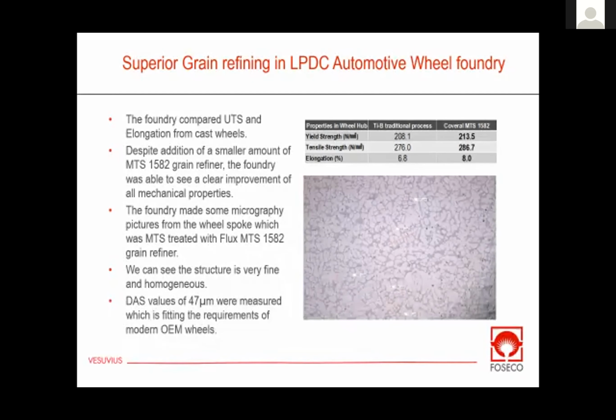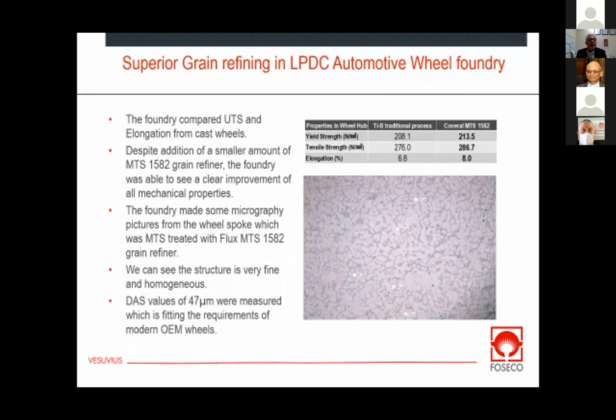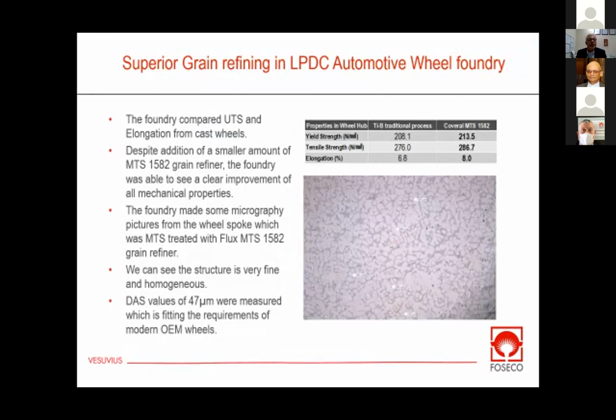When they looked at UTS, yield strength, and tensile strength, they saw exactly the same thing—an improvement. Sometimes it's a small improvement, sometimes a more important improvement in percentage. So this enables me to say that our Coverall MTS 1582 is a far more efficient way to grain refine OEM wheels made in the low pressure process.